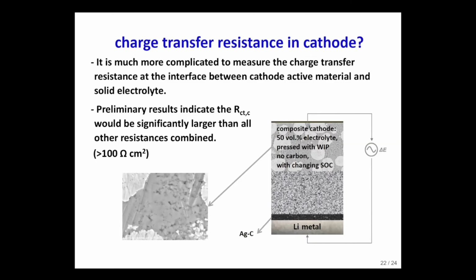This work is still ongoing, but preliminary results with this kind of cell indicate that the charge transfer resistance in the cathode is at least 100 ohm square centimeters. That means this resistance is higher than the sum of all other resistances.